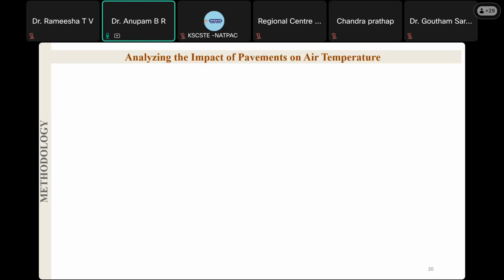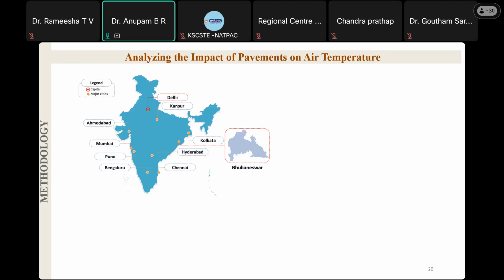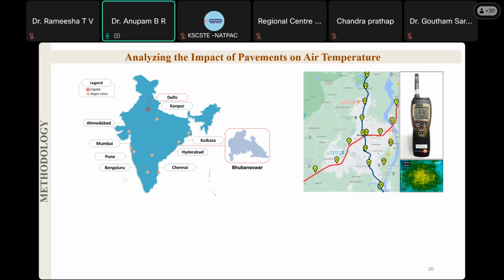So coming to the methodology to analyze the impact of pavements on air temperature, this work was done as a part of my PhD work at IIT Bhubaneswar. So Bhubaneswar was selected as the study area. We conducted vehicular surveys through Bhubaneswar city. We crossed the city from the rural area, went to the city center, again went to the rural area in two cross directions. And at intermediate points, we took the temperature and humidity reading as well as the pavement temperature reading. So temperature we measured just near the surface at different heights. At 1 meter height above the pavement, what is the temperature? 1.5 meter height, what is the temperature?